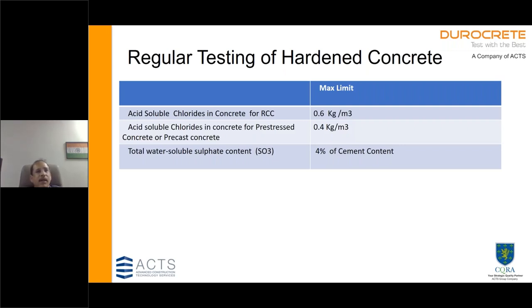Now, many a times we are taking concrete from RMC, and RMC is generally giving certain certificates. Now, how will a client verify the kind of quality control that goes into the raw materials for concrete that is being supplied? That is very difficult for a client. But the easiest thing to do is, you are testing the concrete cubes, send one of the cubes to a lab and check it for acid soluble chlorides and sulfates both. And this test is very easily possible. It is not very expensive. So actually, ideally, you can do it for every pour.